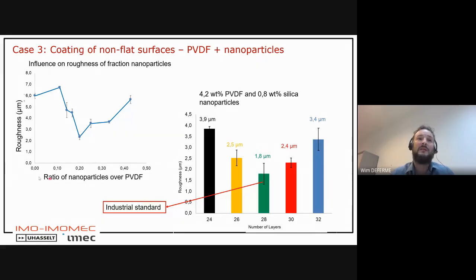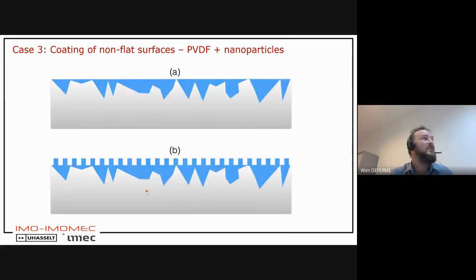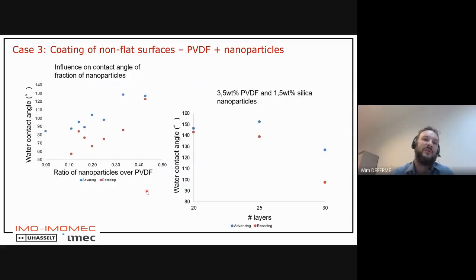So optimizing the ink, the amount of nanoparticles compared to PVDF in acetone, and optimizing that for the number of layers gives a very smooth layer. But the advantage of having nanoparticles in there is also that you can have a specific, repetitive nanoparticle deposition. And that means that you can also use it for hydrophobic or superhydrophobic applications. And that's what we investigated. So for the amount of nanoparticles in PVDF, we measured the advancing and receding water contact angle. And what you see is that it goes up to 130, 140 if you put a lot of nanoparticles in there.